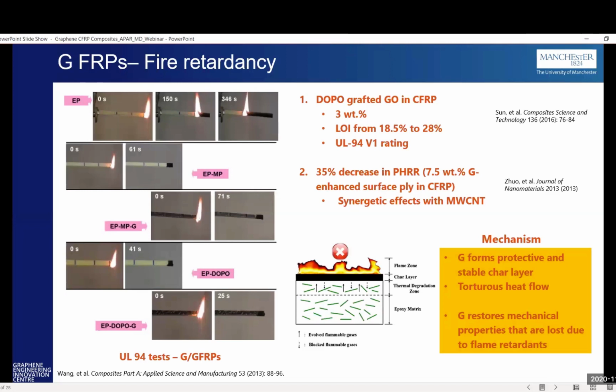The way it works when it comes to the fire retardancy is that when there is fire, the graphene forms a protective char layer, and this char layer prevents the heat from penetrating through the material, which means it is increasing the tortuosity for the heat to go through. And besides that, graphene restores the mechanical properties that are typically lost because of the flame retardants that are being used.